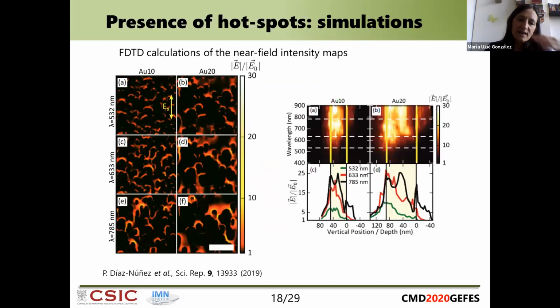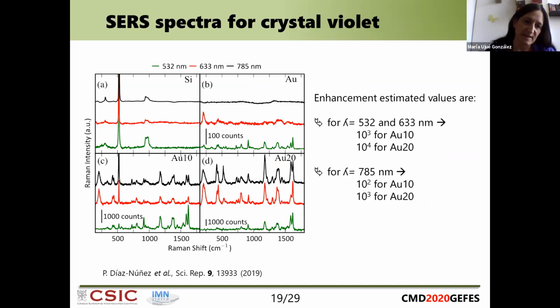And in order then to really see if this was useful to enhance the Raman spectra, we did it. We performed some spectra for crystal violet, and we had as a control the spectra on silicon and the spectra on top of gold. But here you can see that in the spectra we obtained on top of the short and the long nanocolumns, you can really see the features of the molecule much clearer. So we are really having an enhancement compared to the pure silicon or flat gold.